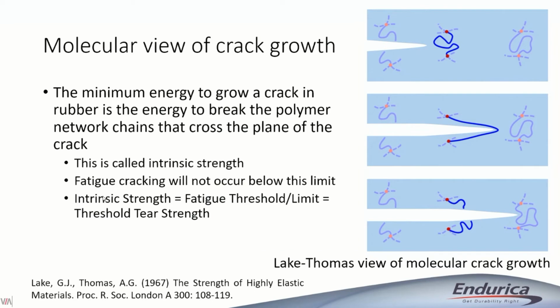Like I said, the intrinsic strength represents the energy it takes to break polymer chains. So here's a picture of a crack growing through a bit of rubber, and you can see pictures of the polymer chain. On one crack face, the polymer chain is attached by a crosslink to the rest of the rubber network, and on the other crack face, it's basically crosslinks where the polymer chains are attached. And so the crack is always breaking the segments of the chains that come between crosslinks. The intrinsic strength is just that minimum energy that it takes to grow a crack and to break all of the chains per unit area. There's a great paper on this, Lake and Thomas in 1967, where they proposed the model that we've been using ever since. It's built on the idea of breaking polymer chains.